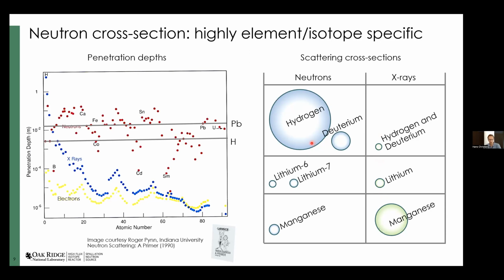Hydrogen has a nucleus consisting of 1 proton. The deuterium has a proton plus 1 neutron. They have the exact same chemical properties, but they look very different to neutrons. Lithium has different isotopes that also look very different to neutrons, whereas in X-rays they still look the same. Manganese looks pretty small to neutrons, and so we can actually easily see lithium within a material that contains other elements. So these are critical things for neutron scattering.